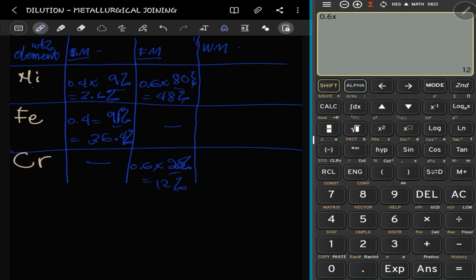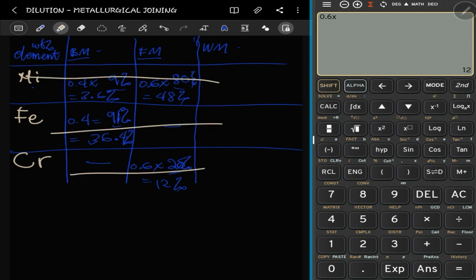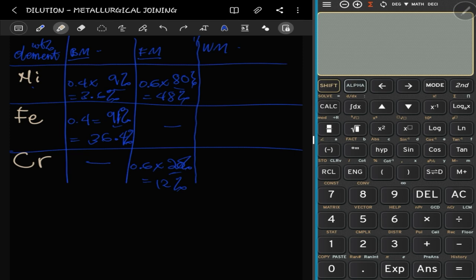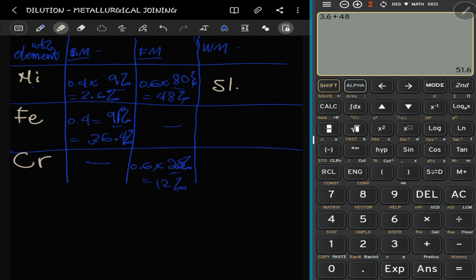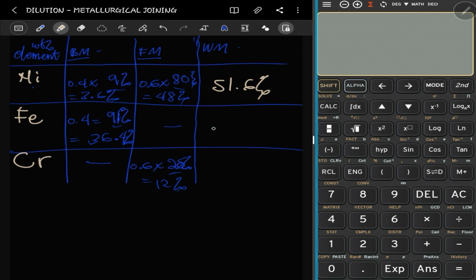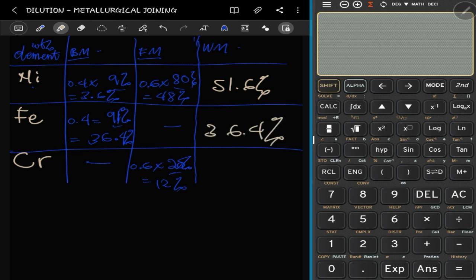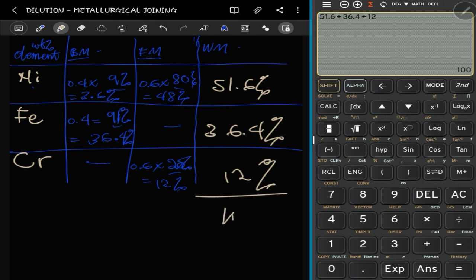Right, now we can add up. We can add up this way, this and this, right? So 3.6 plus 48 is 51.6%. This is just this, 36.4%, and this is 12%. To check if you're on the right path, you have to add them and see if you get 100. 51.6, 36.4, 12, and that gives us 100, right? So basically, this is the composition of the whole weld metal. So now it is clear the amount of chromium in the weld metal. This is the weld metal, and this is the chromium weight percent, right?